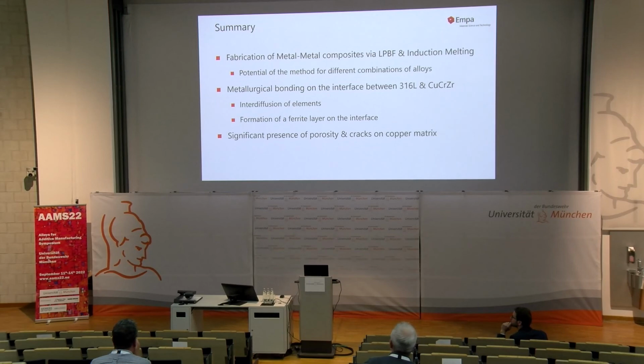So, to end up with conclusions, until now, what we have done is to use laser powder bed fusion with induction melting for the fabrication of composite materials. We believe that in general, the process can have application to different combinations of alloys. So, in principle, what we need is to have some alloys with good printability, like steel or titanium or nickel-based superalloys. And on the other side, we need powders that can be cast with induction melting. Copper is a good example. We have also tried it with aluminium, but in that case, the spheroidization of the powder due to the alumina layer results in an intense presence of not filled lattices, so we have intense presence of porosity in between the steel